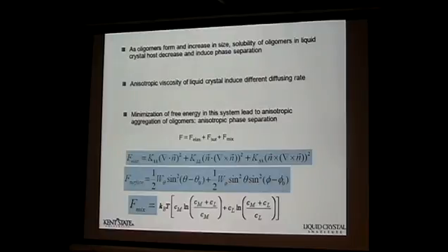So I guess it involves a little bit about the free energy of the system. It includes the elastic energy of the system, the surface free energy, and also the mixing. The mixture means containing two different components, for example, depending on the concentration of monomer and the concentration of liquid crystals. So the Flory-Huggins equations should be added into this total free energy of the system, because of the surface energy. If you have a surface alignment, it depends on the structural deformation, and that one is kind of a minimum. But I think the control factor is here: the free energy of the system, the elastic free energy, and also the phase separation, the mixtures forming this.